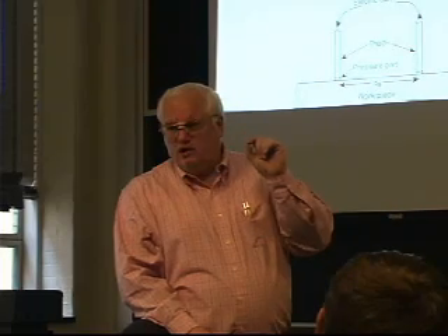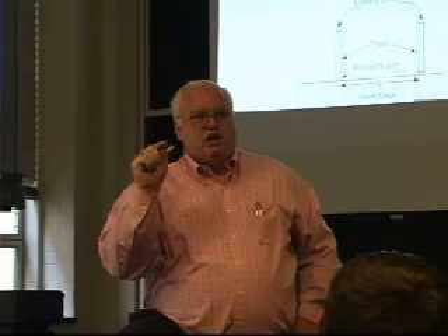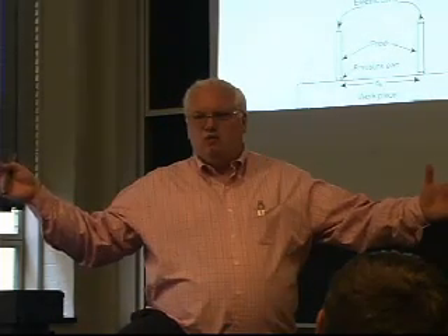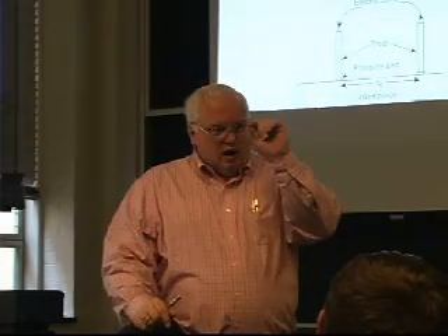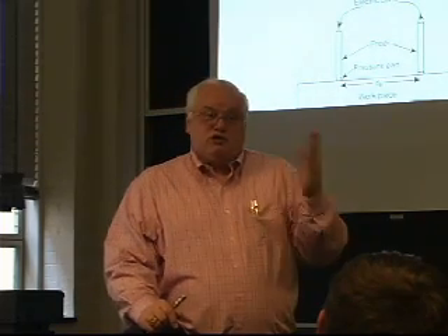They have this little bulb, Brian could show it to you tomorrow, a little bulb full of very fine magnetized iron powder, and you squirt it on there, and you can buy them red and green, different colors, and you'll see it line up. And that's how, as I mentioned, when the Seawolf submarine, it wasn't an inspector that found the very fine cracks that were less than 1/8 of an inch. It was the guy who was grinding the weld smooth, and he wasn't doing an inspection, putting iron filings on there, but you've got this great big long submarine which develops some residual magnetism from the Earth's magnetic field, and he saw that the grinding particles were lining up. Well, he was basically doing a very sensitive magnetic particle test, and he was smart enough to know he didn't usually see that, and that didn't look right.